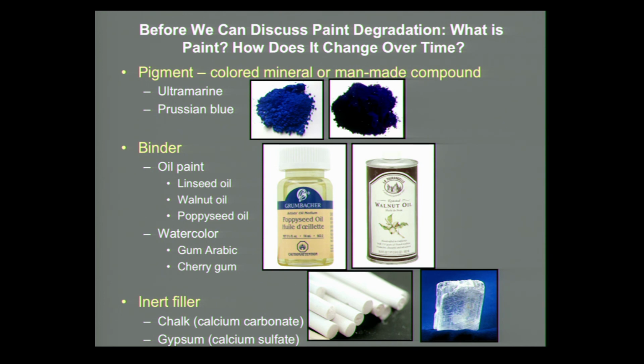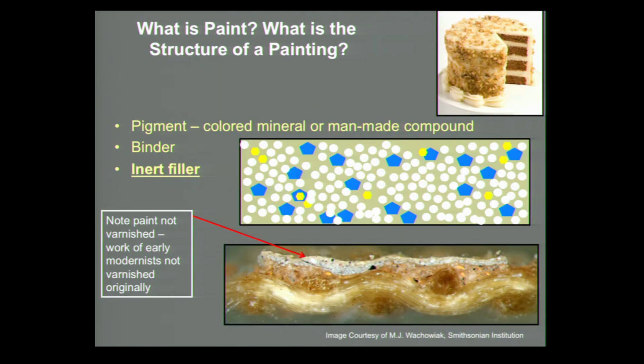But it turns out that these are actually minor components of the paint, and that the major component of paint is actually an inert filler, something like chalk or gypsum. And this is really the paint manufacturer trying to maximize their profit by using the largest amount of the most inexpensive component possible and the smallest amount of the colored pigments, the most expensive components. So this is a cartoon of what a paint really looks like. Most of what you're seeing is the white filler material, and then you've got the occasional pigment particles and the binder that holds it all together.